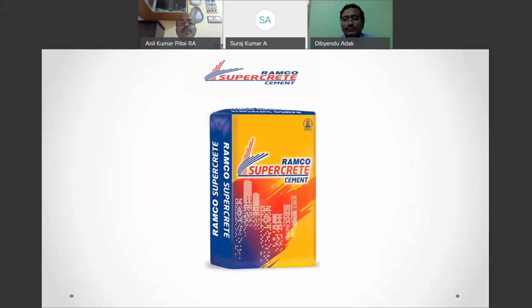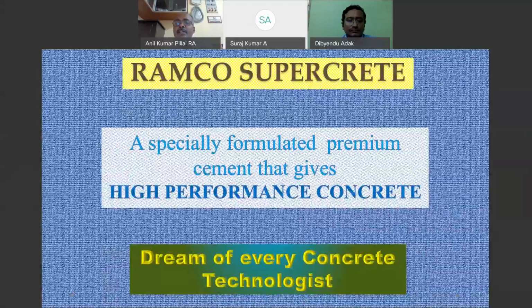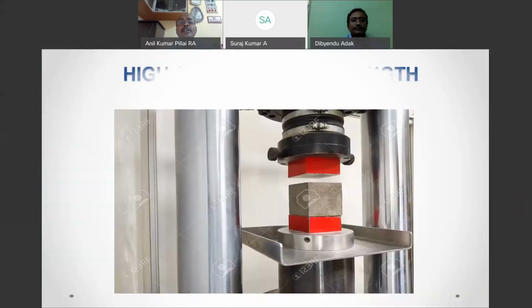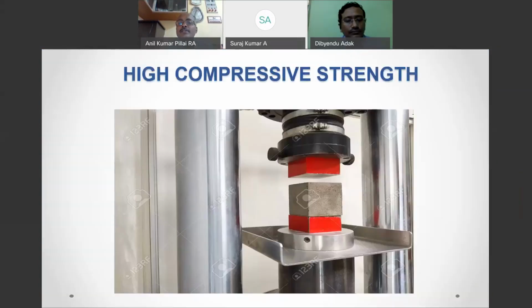Of course, we have got a number of responses as far as Ramco Supercrete is concerned. Ramco Supercrete is a specially formulated cement, which gives high performance concrete, high compressive strength, and at the same time low heat of hydration, low lime leaching, and a better durable concrete is what you get. The response we have received was that they are able to get the 28-day compressive strength of concrete within 7 days.